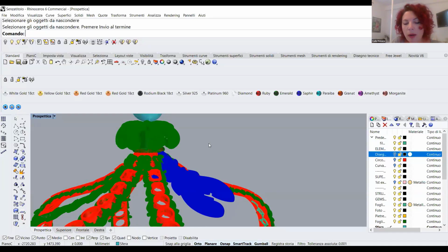Maybe if we use a cube, not a square, you could have some problem in the angle, because during the casting, maybe you could have some dirty element inside, or maybe metal adding in the angle. And for that, this type of interlocking mechanism doesn't work. With the sphere and this type of tolerance, always the assembly is very simple, and we don't have a problem during the casting. If I will show you the second file about that, maybe.